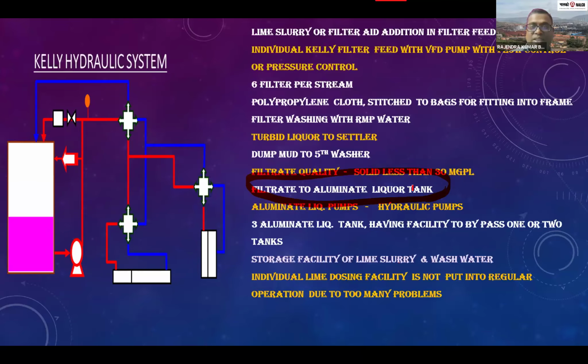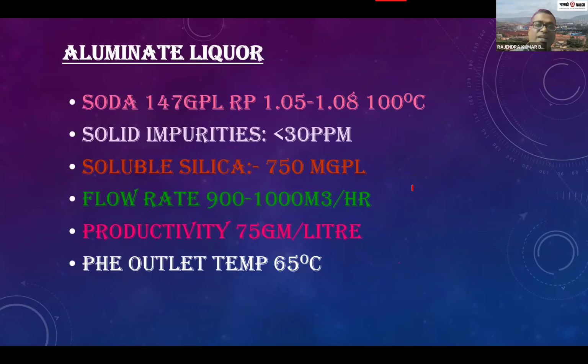Individual lime dosing facility is not put into regular operation due to too many problems. The aluminate liquor, this is our product. Soda 147 GPL, ratio 1.05 to 1.08, temperature 100 degrees centigrade. Solid impurity is less than 30 ppm. Soluble silica 750 mg per liter, flow rate 900 to 1000, and productivity 75 gram per liter. Outlet temperature is 65 degrees.